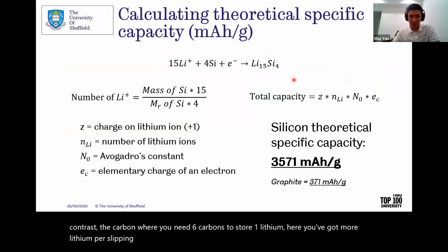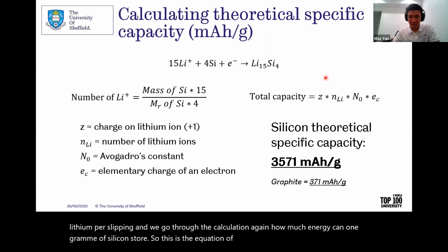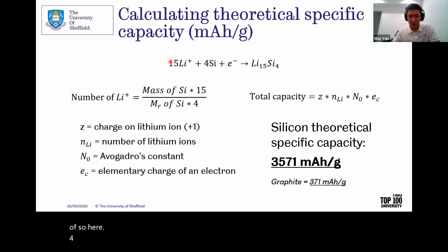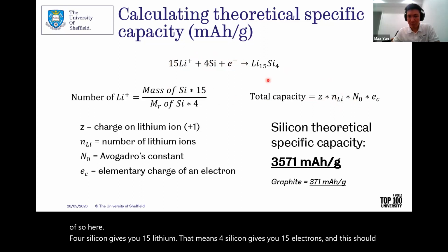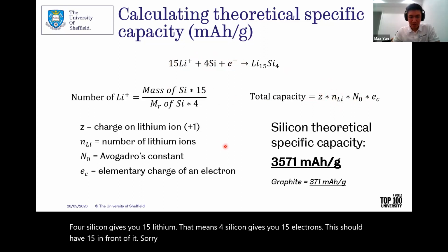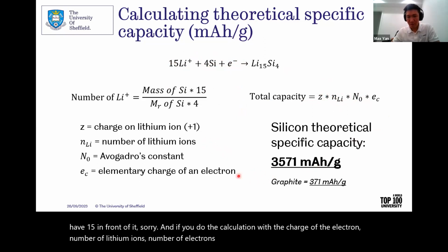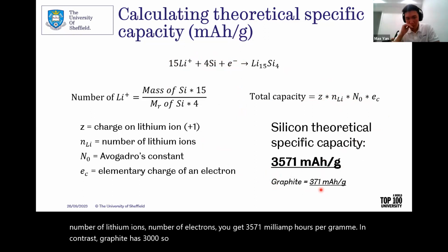And we go through the calculation again. How much energy can 1 gram of silicon store? So this is the equation that I've shown you before. Here 4 silicon gives you 15 lithiums. That means 4 silicon gives you 15 electrons. This should have a 15 in front of it, sorry. If you do the calculation with the charge of the electron, number of lithium ions, number of electrons, you get 3,571 milliamp hours per gram. In contrast, graphite has 371, so it's nearly 10 times the capacity. This is why silicon is so important.